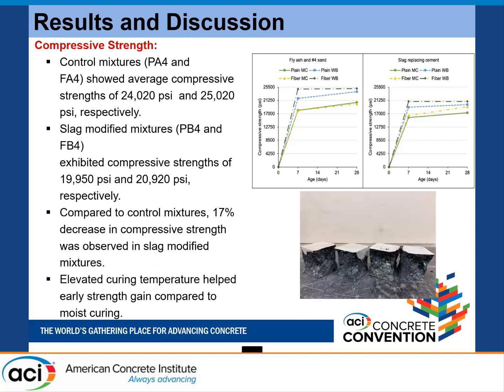And compressive strengths, if you look at it, the control mixes had average compressive strengths of 24,000 psi for plain and 25,000 psi for fiber. But the slag mixes produced slightly lower strengths, about 19,000 to 20,000 psi with plain mixes and more or less similar strengths for the fiber reinforced mixes. Obviously, this is understandable. Nevertheless, with the penalty in compressive strength, we saved a lot of cement and cost. And 17,000 psi is strong enough to apply in bridge applications. But we are still working on improving these strengths. Later I will show you that we finally hit the 24,000 mark even with slag in the next few slides. You will see the 17% decrease in compressive strength we observed, but later on we were able to recover it by doing something else.